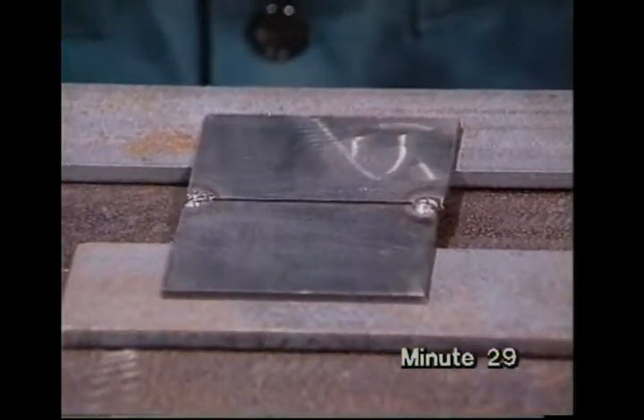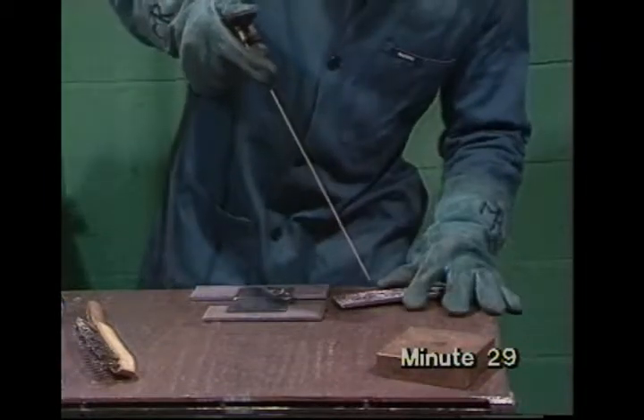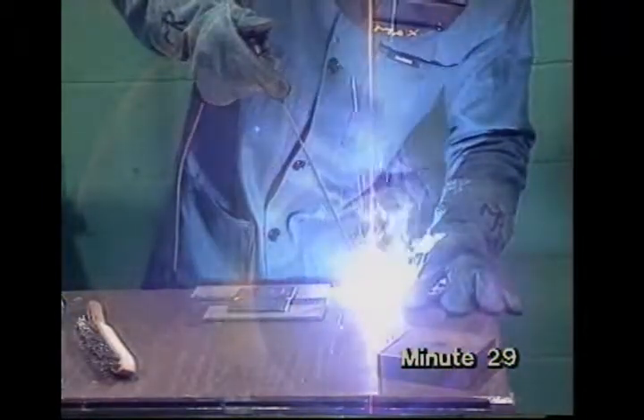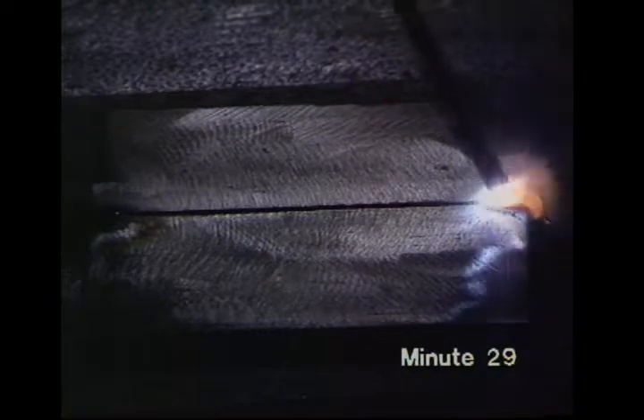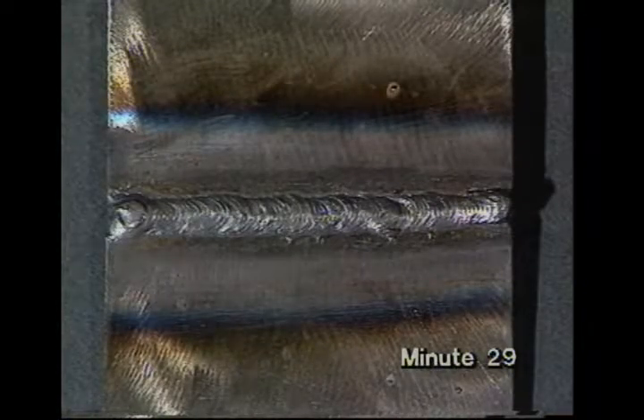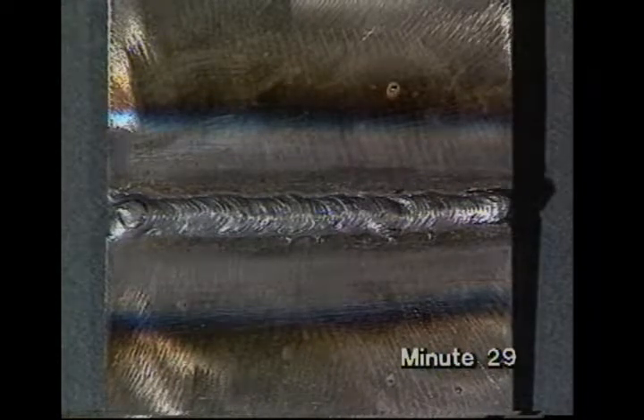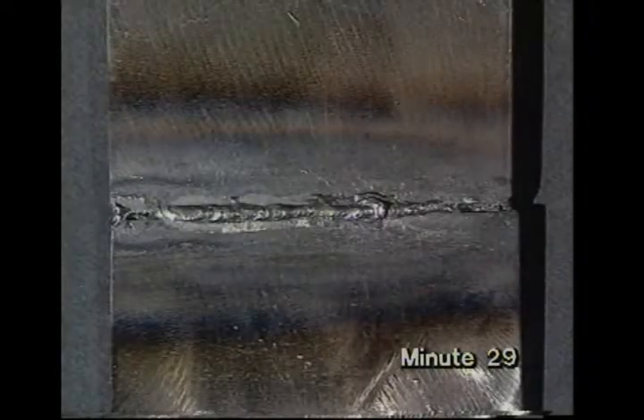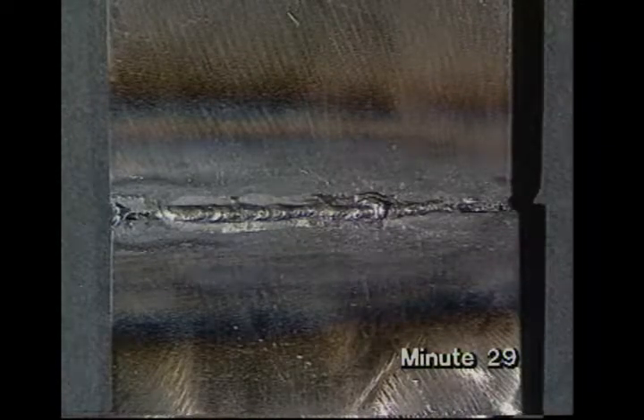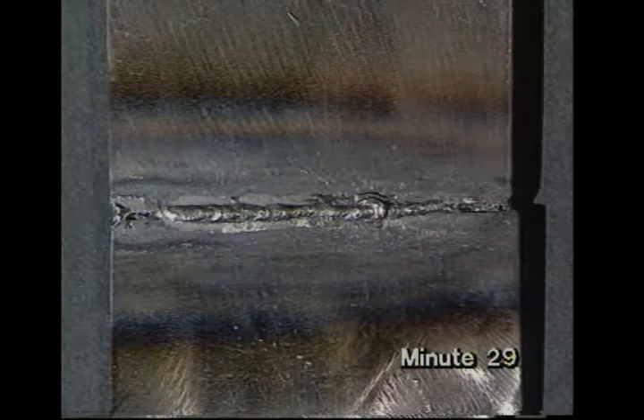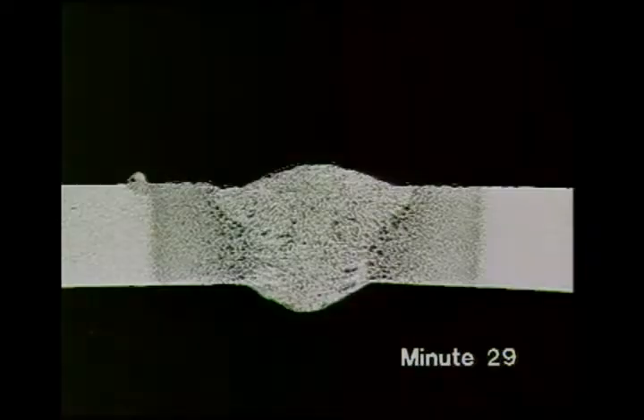Prop it up above the bench, then weld it just like the bead on plate you started with. This should leave a weld which extends beyond the gap between the plates. And when you look on the back, the weld metal should have gone right through and just penetrated beyond the surface. The macro section shows the smooth top and bottom profiles, and there's no sign of the original edges.